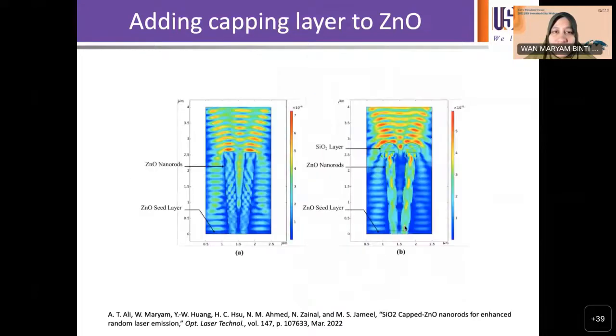So this is something that we observe, and to look at this further, to understand the effect from SiO2 further, we used, I forgot the actual name, finite element method, yeah? So we use finite element method to identify, and we notice that 100 nanometer of SiO2 layer shows waveguiding properties with the mode spectrum long enough to tolerate several periods longitudinally. So you increase the intensity of the light strongly. So we see more confinement of light occurring when we have around 100 nanometer of the SiO2 layer.